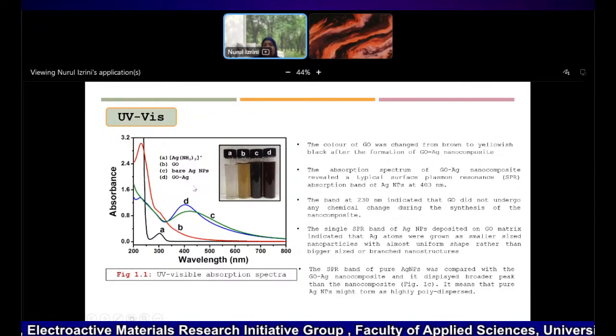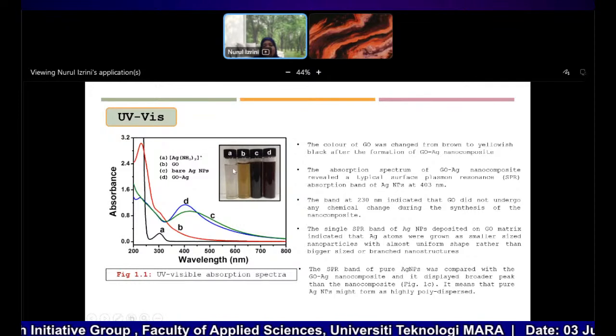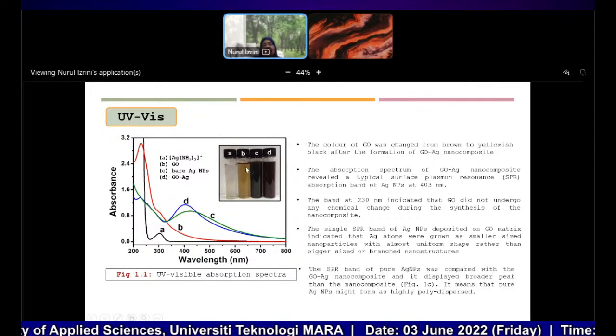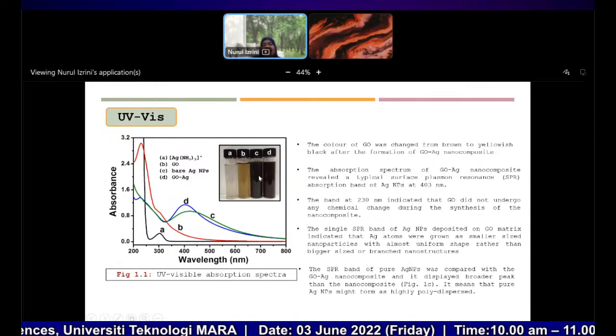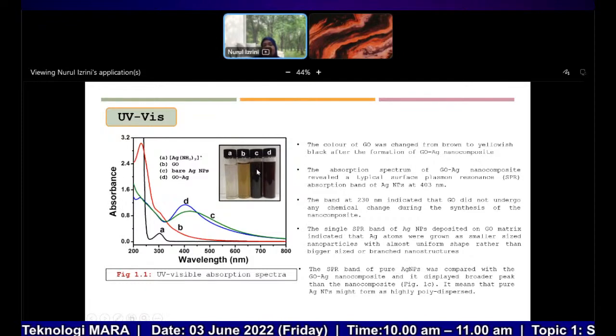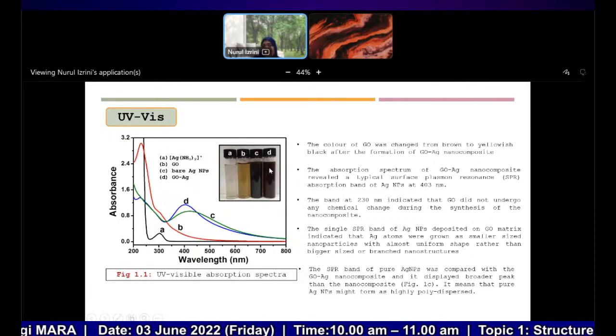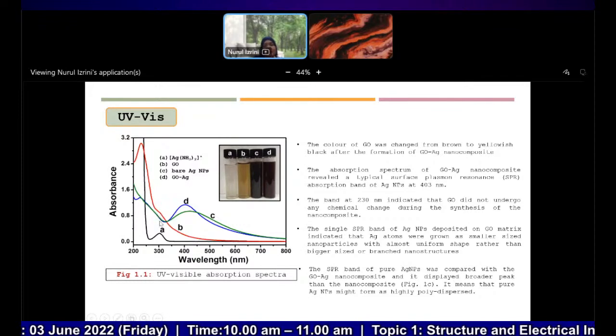On top of our GO sheet, we use UV-visible spectroscopy and test with several samples. For example, here we just use AG ammonia complex, without any GO, just AG ammonia alone. We also test GO, graphene oxide alone, and the bare AG nanoparticles, which is without GO, only the AG nanoparticles. And then this is our nanohybrid, which is GOAG. So based on this UV-Vis spectra, we can see that...